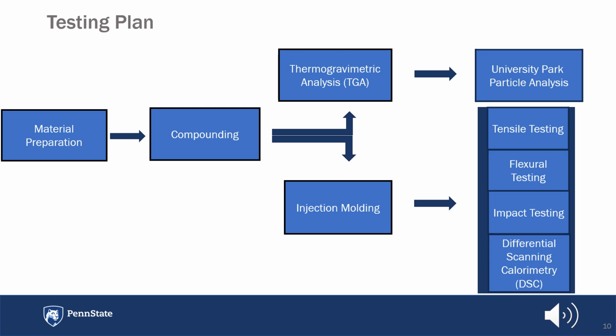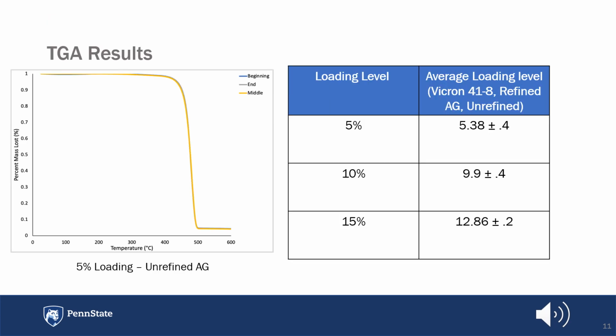known as DSC. It was important to make sure that we were getting similar loading levels in terms of our calcium carbonate and polyethylene compounds. For our 5% loading level, we had an average of 5.38 plus or minus 0.4 for that of the Vicron refined and unrefined material. Additionally, our 10%, we had an average loading level of 9.9 plus or minus 0.4. For our 15%, we had an average loading level of 12.86 plus or minus 0.2.